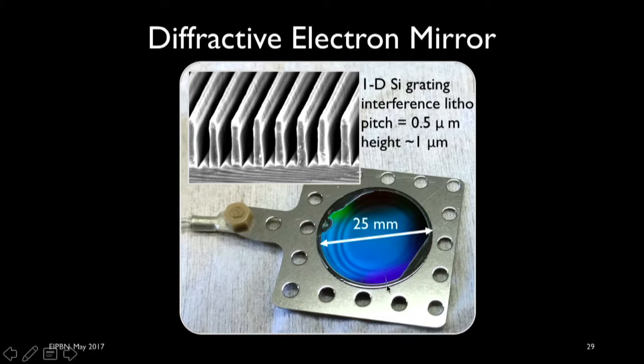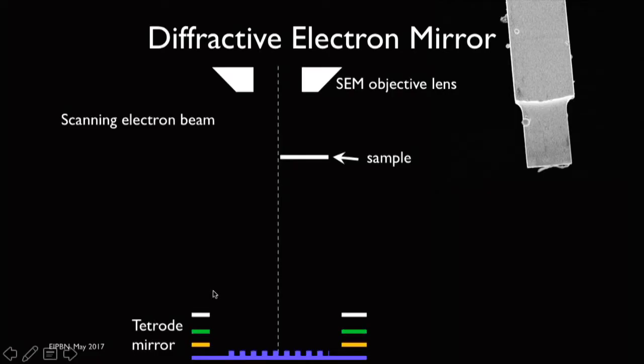So what we did was we fabricated this diffraction grating on the silicon wafer and basically stuck it on one of those stainless steel plates, which in this case is the mirror plate, the bottommost plate in that mirror assembly. And then when we apply a potential to the mirror, those sinusoidal potentials are formed on top of the grating.